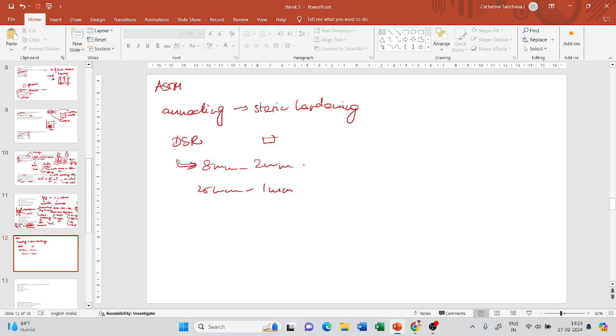Okay? After you have heated and poured the sample, again it will start forming a structure, right? Because it is again kept at a constant temperature. Beyond 4 hours you cannot test this sample, and you cannot reheat this. You can maybe reheat the same sample and use it, but you cannot test the sample because it is expected to again have steric hardening. Okay, so steric hardening is one which occurs at ambient temperatures or ambient constant temperatures. Constant refers to isothermal, right? Iso is same. So isothermal temperatures or ambient temperatures.